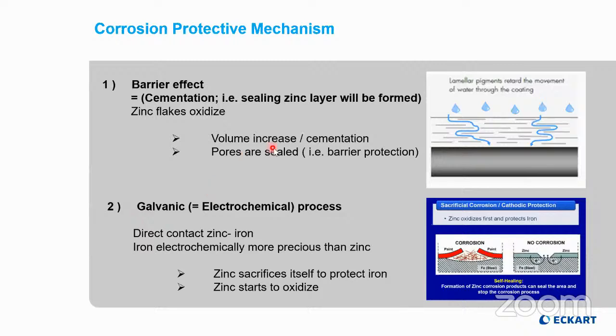The barrier effect of especially zinc flakes can be easily detected from this picture. The zinc flakes align in the paint film and by that form a very long pathway for the moisture to penetrate to the steel substrate, and because of this barrier, moisture is repelled for a certain period of time from the steel substrate, so corrosion protection can occur.